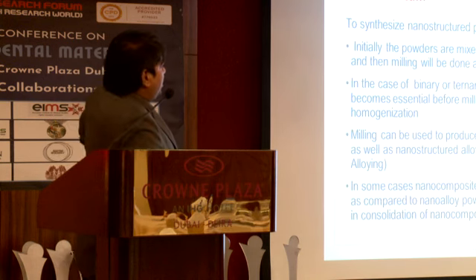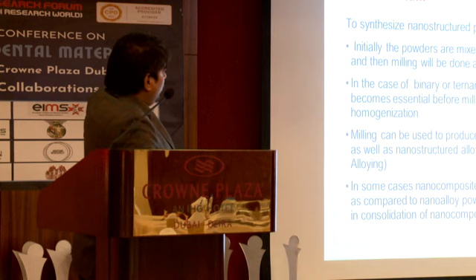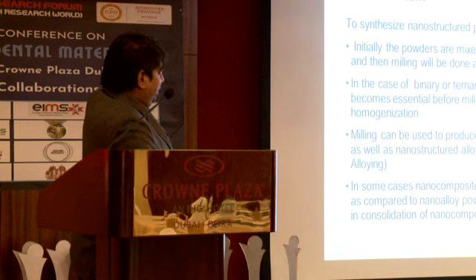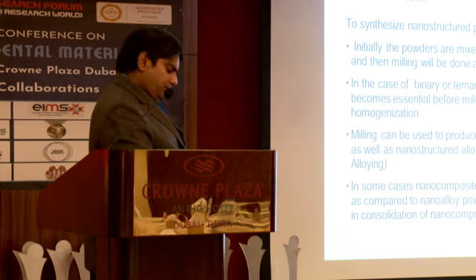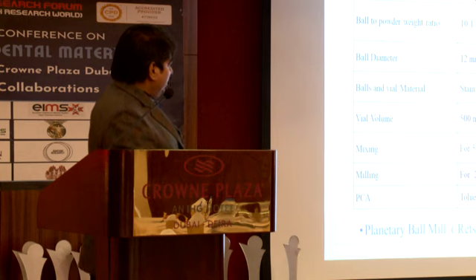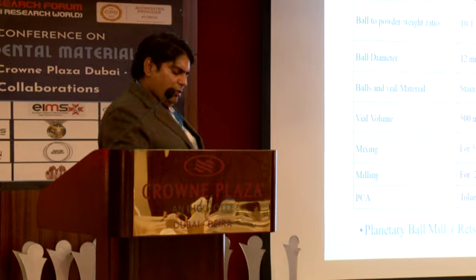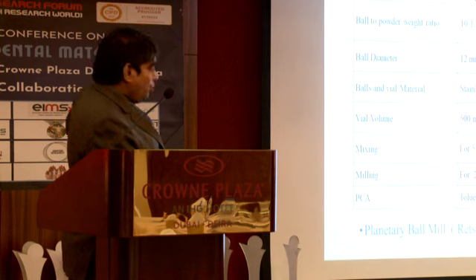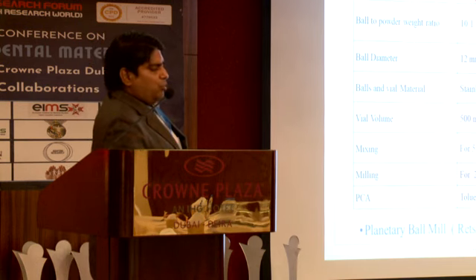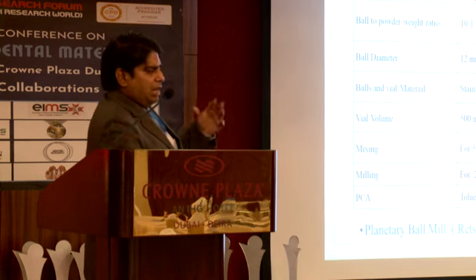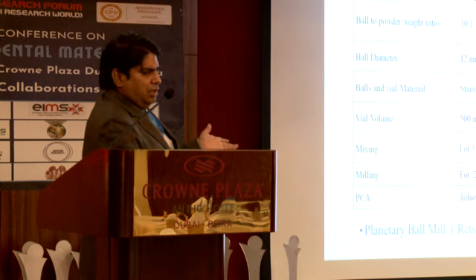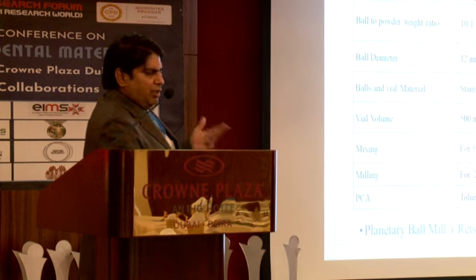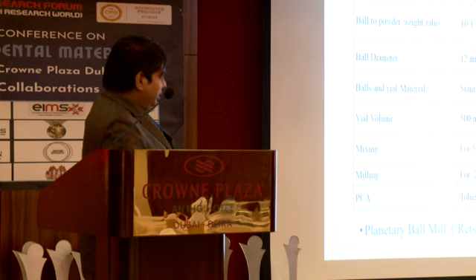So these are the ways to synthesize nanostructured powders. Initially at lower RPM, in the case of binary and ternary compositions, will ensure the homogenization, and then in some cases you go for nanocomposite powders, in some cases for alloy powders. These are the parameters of the mill: ball to powder ratio, ball diameter, ball material all become very important. The energy transfer depends on the RPM, the speed of rotation, and the type of ball material used becomes very important.